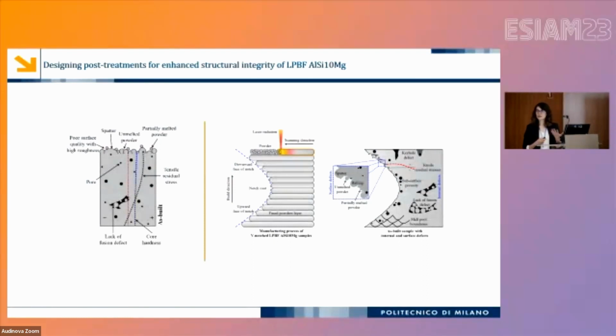As we are working with laser powder bed fusion technology, we know that there are many different types of defects: bulk defects like pores, lack of fusion, tensile residual stresses, and anisotropic microstructural characteristics. But at the same time, we have a lot of surface defects. It's a big problem at the moment for all additive manufacturing technologies, because we always have very irregular surface morphology.